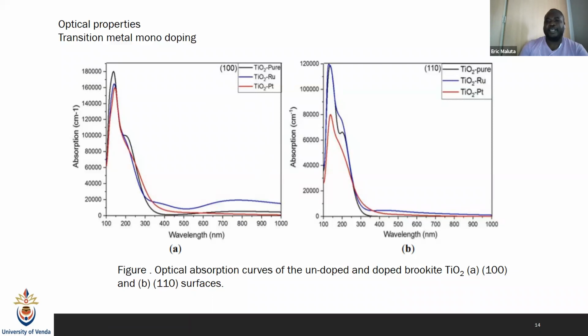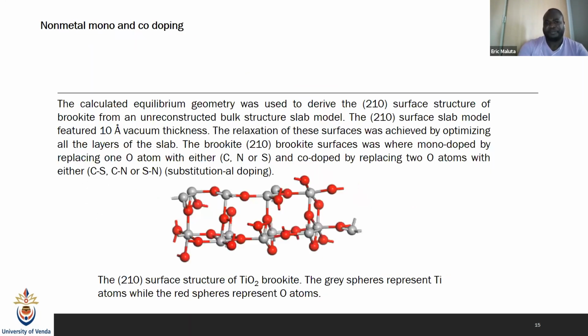And in the current situation, people are looking at organic dye molecules because they are cheaper and easy to synthesize. And then it means if the Brookite surface can also absorb from the visible to the near infrared, then the organic dye molecule also will be able to inject more of the electrons, which can diffuse more on the Brookite surfaces, because now we have reduced the band gap.